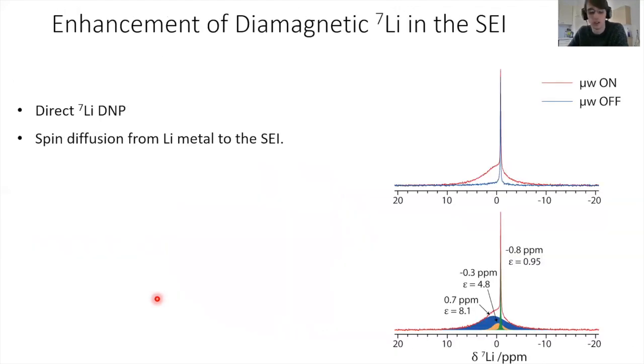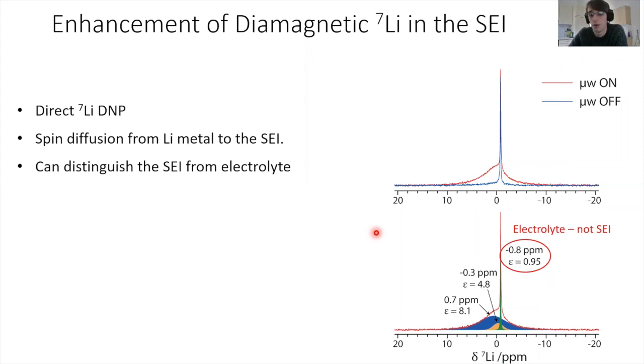So just to quickly show you some of these results, in red is with microwaves, blue without microwaves. This is the diamagnetic lithium spectrum now, so the spectrum around 0. And you can see that there's an enhancement on irradiation of microwaves of the metal. But importantly, this isn't uniform. So this sharp peak here is the electrolyte. It's residual salt in the electrolyte that has been washed away. That's not in the SEI. It's not in contact with the metal, and so it's not enhanced. Whereas these other species are in the SEI, and they are enhanced. We can also look at their relative enhancements, and that tells us something about the spatial distribution relative to the metal.